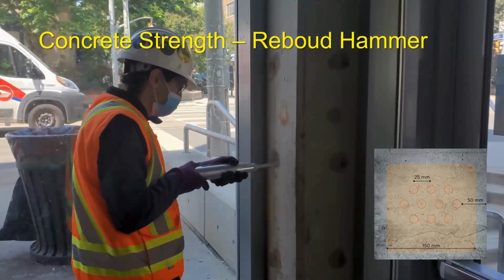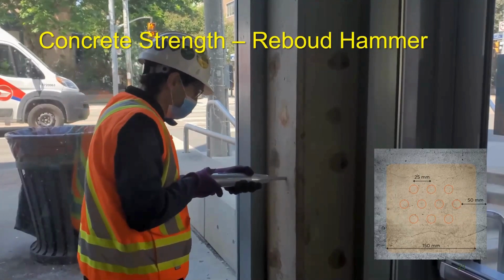Traditionally, we used to correlate this number to the strength of concrete. We know that that is now no longer 100% valid. So right now we recommend that people use more project-specific calibration curves to correlate the rebound number with the strength of concrete. But it is also worth noting that there are new codes, like the Euro norm code, where you can use the rebound hammer number to classify the strength of concrete, which will significantly reduce the amount of coring that you might need in a large-scale project.